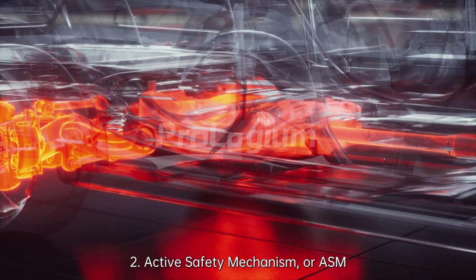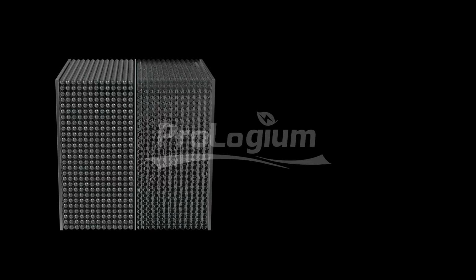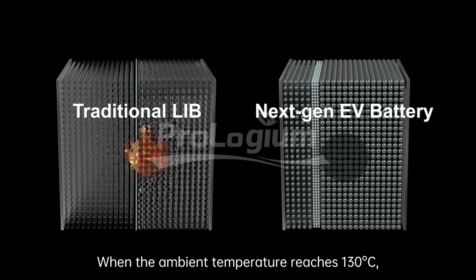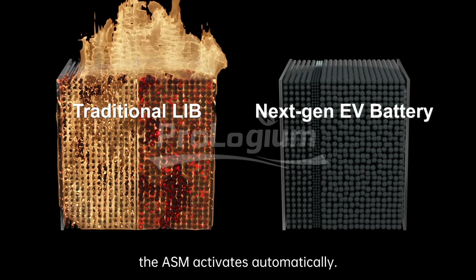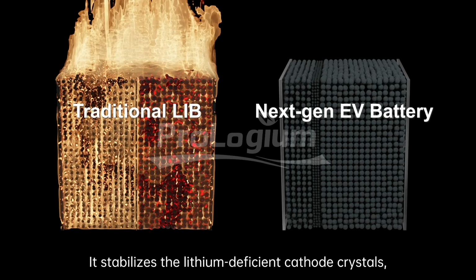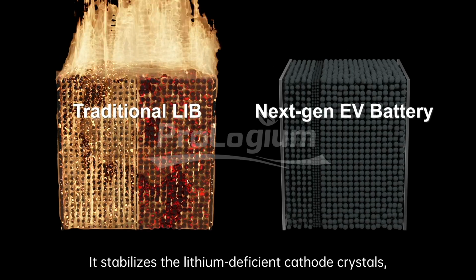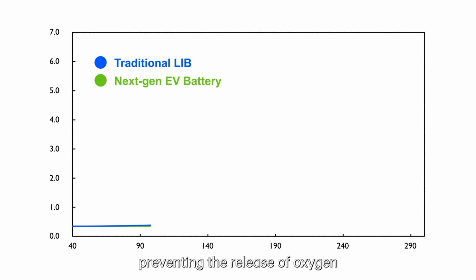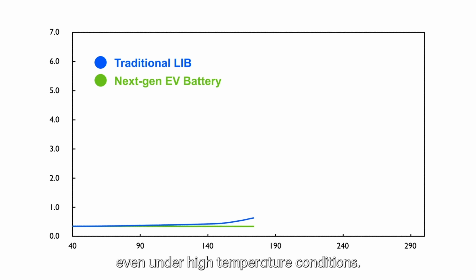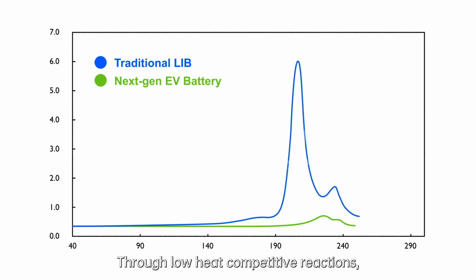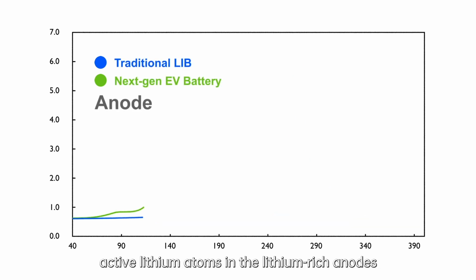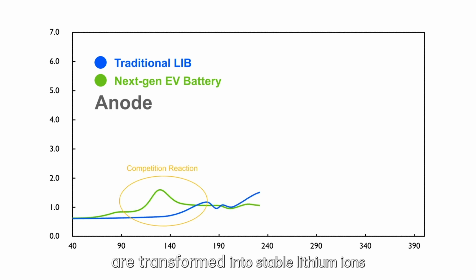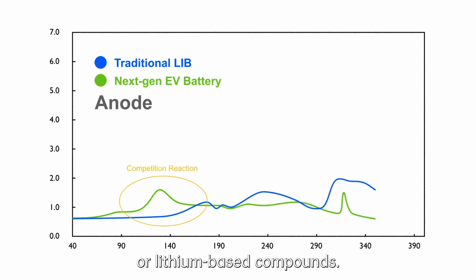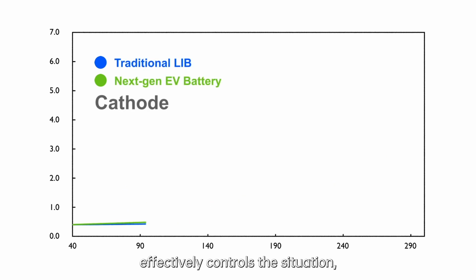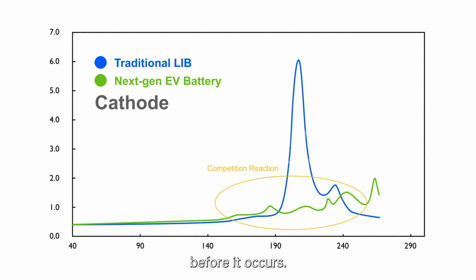2. Active safety mechanism, or ASM. When the ambient temperature reaches 130 degrees Celsius, the ASM activates automatically. It stabilizes the lithium-deficient cathode crystals, preventing the release of oxygen, even under high temperature conditions. Through low-heat competitive reactions, active lithium atoms in the lithium-rich anode are transformed into stable lithium ions or lithium-based compounds. This proactive response effectively controls the situation, preventing thermal runaway before it occurs.